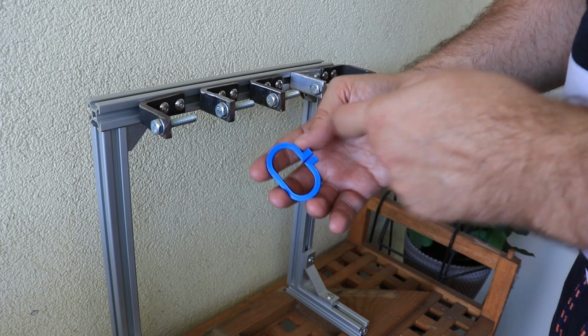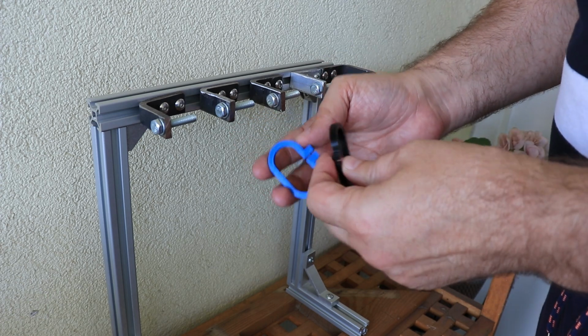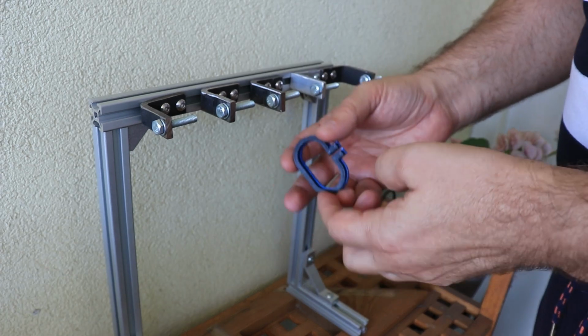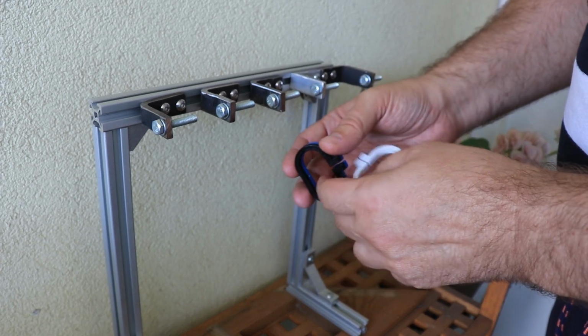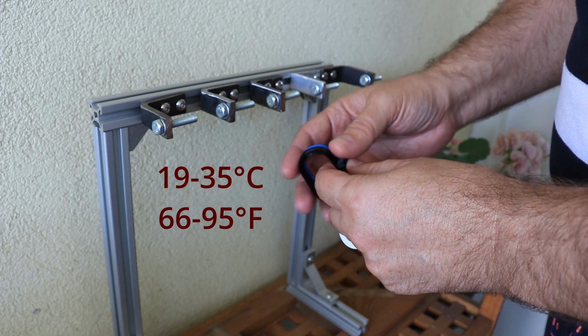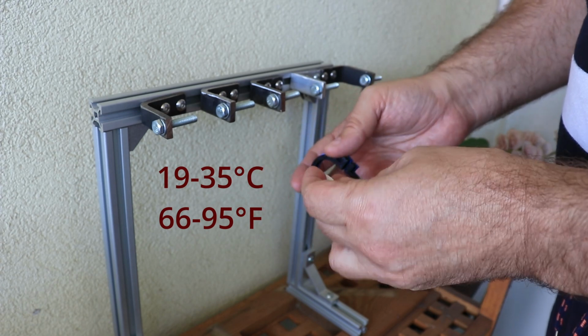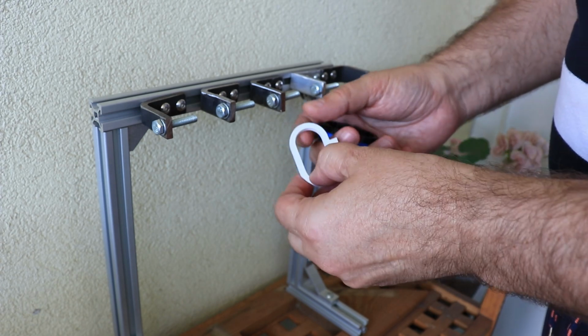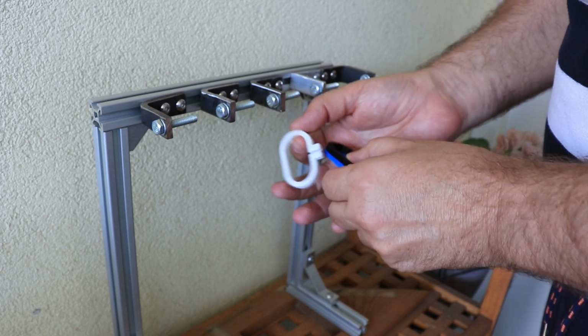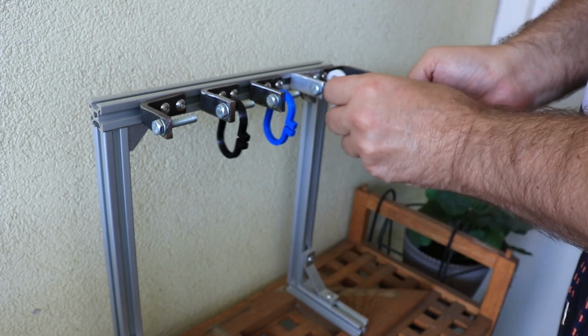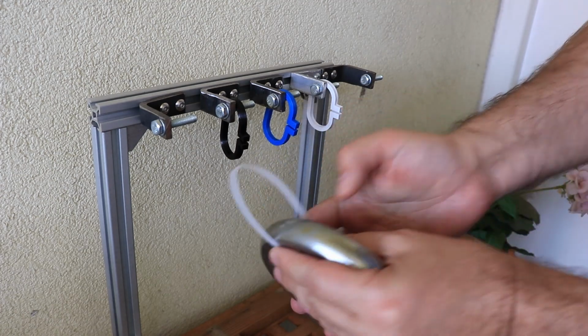And since this creep test depends on the environment temperature too, and now the next 5 days will be quite hot, between 19 and 35 degrees Celsius during the day, I will add for the reference, this is IZOD ABS Plus. And now adding the load.